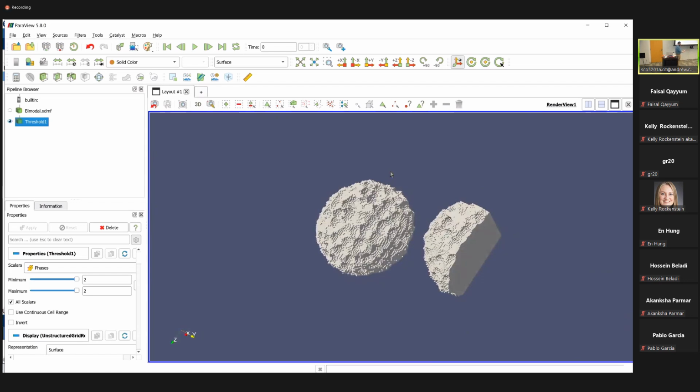This is clearly not how a real abnormal grain would look. So I would never recommend using this to try to create an actual bimodal structure. But what people have done, and what you can do, is use this as a starting point and then put it into SPPARKS, something that's actually going to do an evolution. The nice thing about this is it lets you control exactly what the initial state is, which could be hard to do a priori from a physics-based approach.